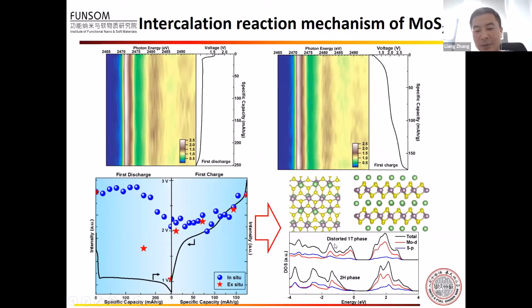To understand this, we perform some simple DFT calculation. We can see that lithiation can induce the phase transition of moly sulfide from 2H to 1T. For both 2H and 1T phases, they are semiconductors with a band gap of 1 eV. Because of this, the in-situ results are not relaxed for the moly sulfide. Therefore, the lithiation degree is always lower compared with the ex-situ results, because the ex-situ samples have enough relaxation time.